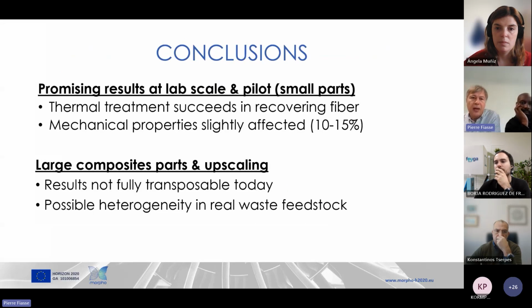Okay, so the main conclusion. We have got promising results at lab scale and, to some extent, at pilot scale on small parts of composite. So thermal treatment succeeds in recovering the carbon fiber with good mechanical properties. What we need to investigate further is large composite parts, so the upscaling, homogenization of the pyrolysis temperature and so on. So results are not fully transposable today at industrial level.